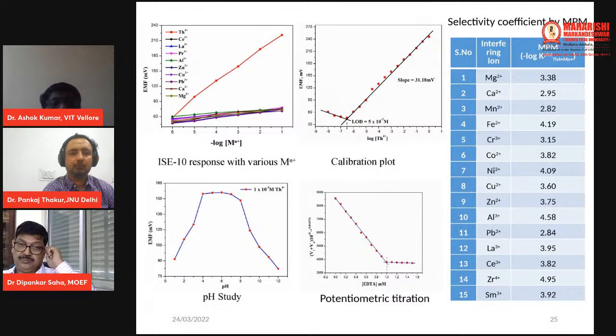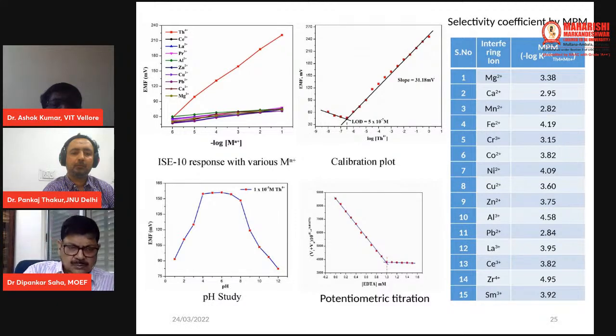And we also studied the other sensing properties. You can see here, for all other metal ions, it shows a response like this. Only with thorium, it shows a unique response. The calibration plot also shows the detection limit up to this particular level. And for the change in pH, you can see it worked in the region from 4 to 8. This particular sensor is also used as an indicator electrode.